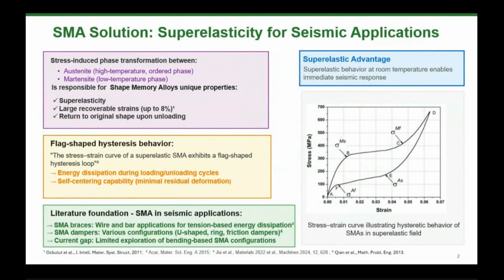And shape memory alloys are one of the possible solutions to overcome these limits, thanks to their property, that is the superelasticity. The superelasticity, as you probably know, is the ability of the alloy to have large recoverable strains up to 8%, and return to their original shape upon unloading. And it is due to a stress-induced phase transformation between the austenite, that is the high temperature and ordered phase, and the martensite, that is the low temperature phase.